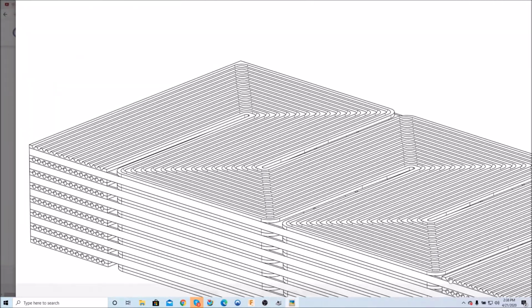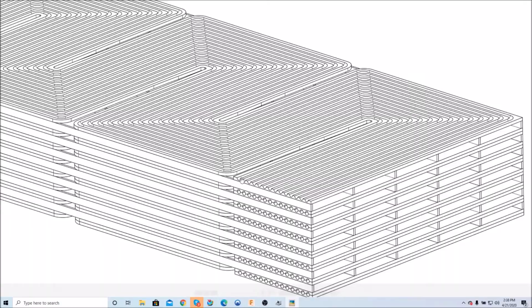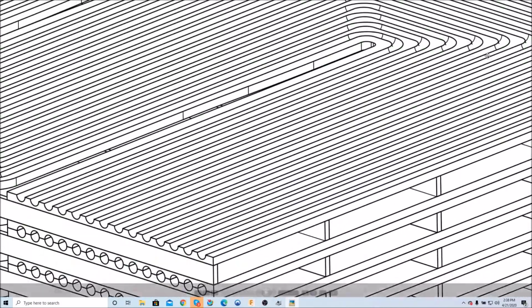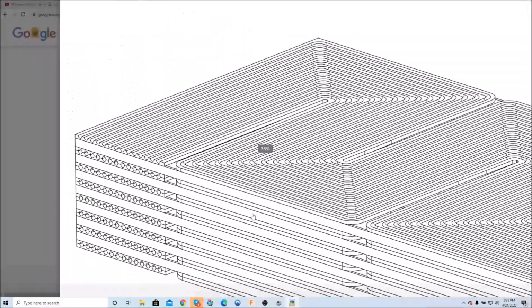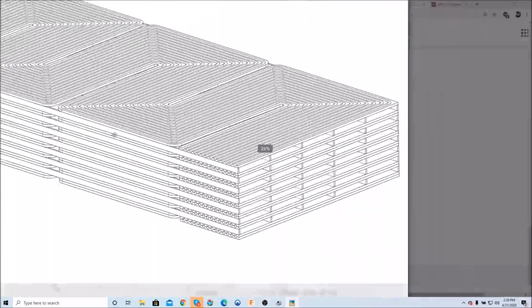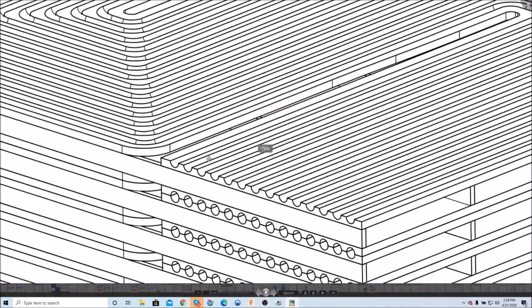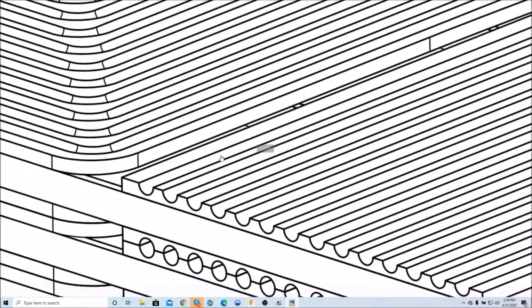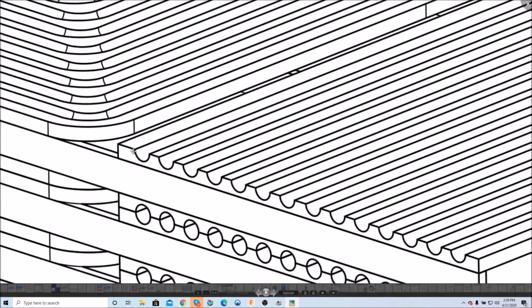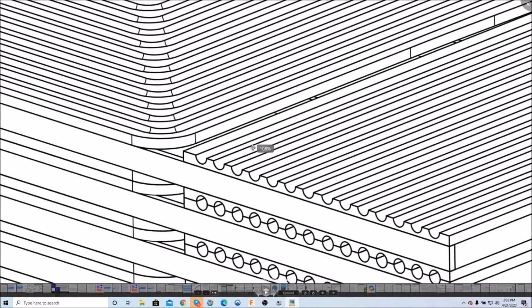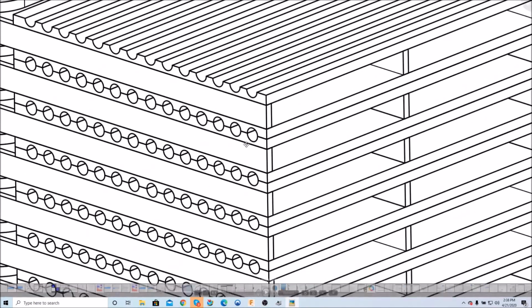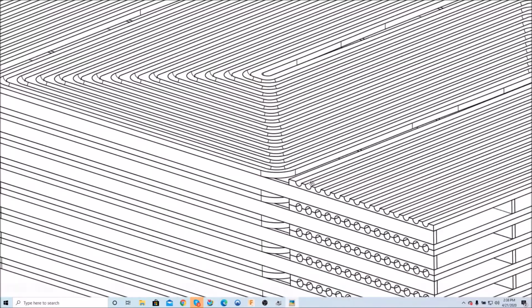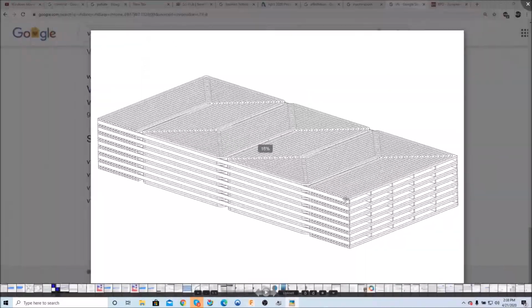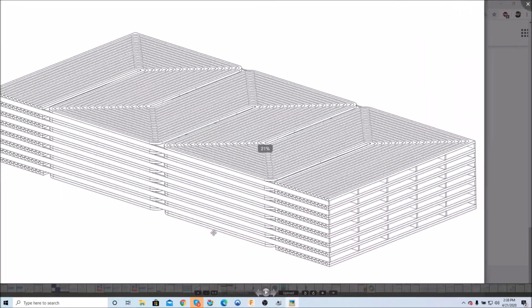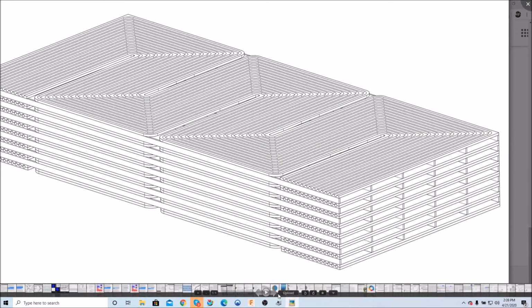Here is an example of a cracker channel plate. So you have this plate, which could be made of various metal alloys, ideally those with a high thermal conductivity. And the grooves are lined, again, using wetness impregnation with the catalyst. And then those are stacked upon each other, and you have a gap between the catalyst plates, which permits the flow of a hot gas that could be combusted, this hot air with the heat provided by burning hydrogen.